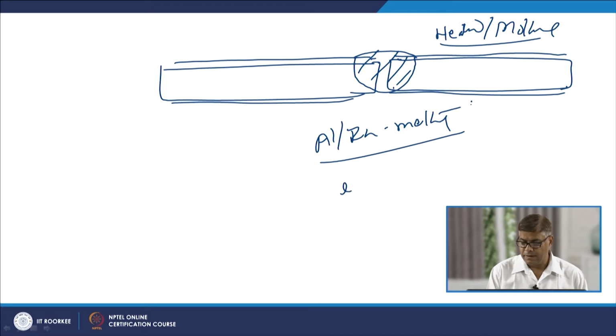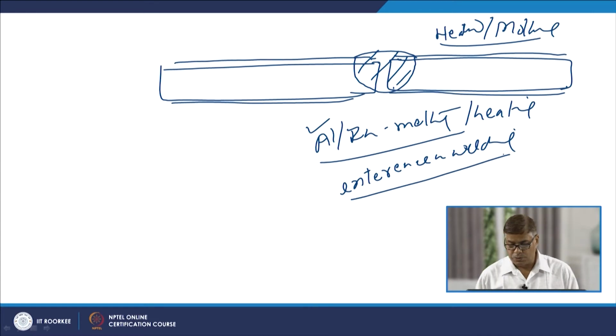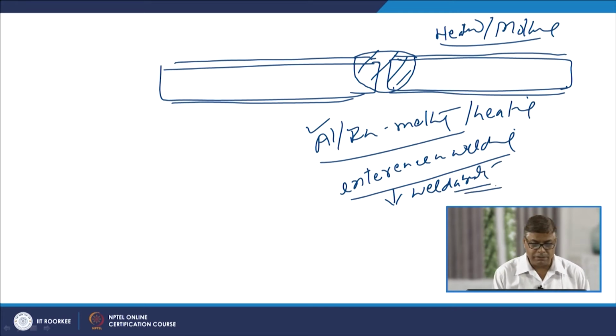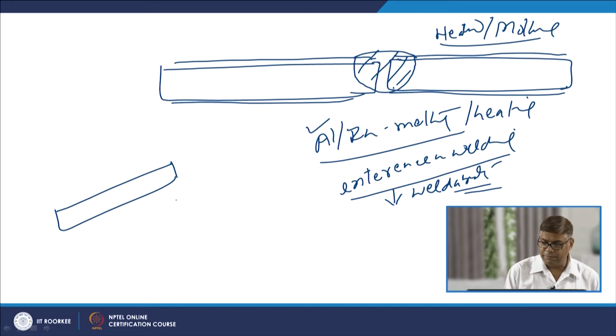So, the heating and the melting combination of the zinc and aluminum leads to the interference in welding in different ways. So, this interference of the aluminum and zinc due to the heating and subsequently in molten state leads to the reduction in the weldability of these steels. So, in general if we compare the carbon steel with coating and without coating, then the coated steels will have somewhat lower weldability than the uncoated or the bare carbon steel sheet.